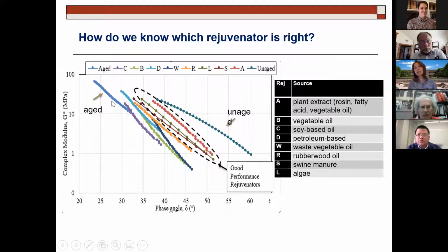This blue is aged, all the way to the left. Obviously, when you say I want to go from aged to unaged, you are moving toward that. Most of these rejuvenators help you move toward unaged. But the caveat here is, look at this violet one, for instance, or even this blue. It moves a bit, but it doesn't even change the slope. It's as steep as the aged one.